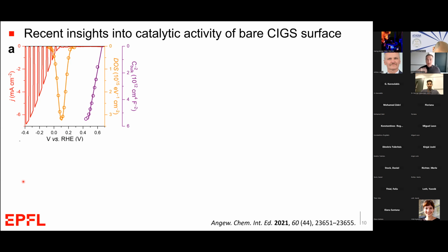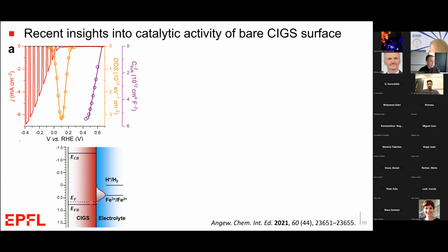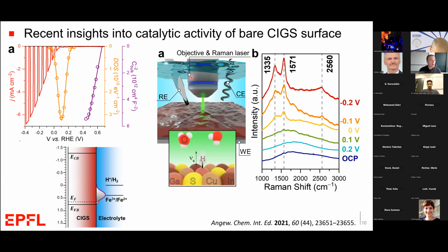So we've used techniques like electrochemical impedance spectroscopy to identify the surface states on these bare CIGS surfaces, which we can attribute to driving either the recombination or the hydrogen evolution reaction. In fact, using techniques like operando Raman spectroscopy, and changing the applied potential where we have hydrogen evolution, we can see the introduction of the gallium hydrogen bond, which suggests that a gallium site on the surface is actually responsible for the catalytic hydrogen evolution reaction. In fact, if we put these two results together, we can come to the conclusion that avoiding the formation of these gallium vacancies is really crucial to achieve the high activity in these sort of films.